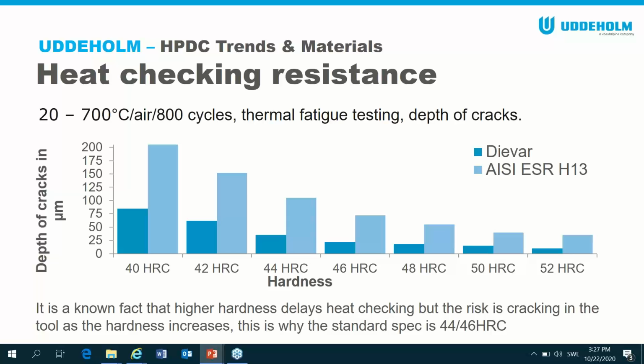So let's pick a hardness. So let's say 44 Rockwell. So you can see at 44 Rockwell, it's room temperature to 700 degrees C, 800 cycles, this test up and down. So Dievar's got a crack of about 30, 40 microns deep maybe, and AISI ESR H13 is about 100. So there's a huge difference between the two.